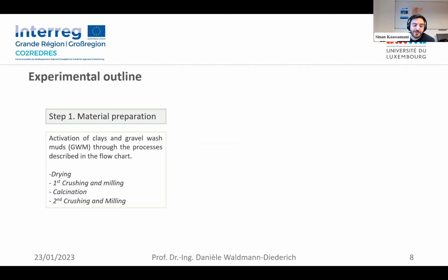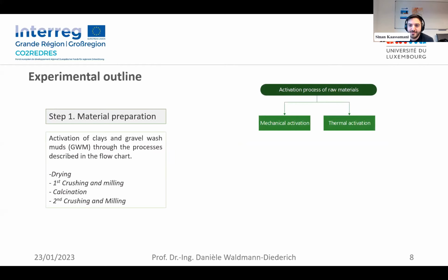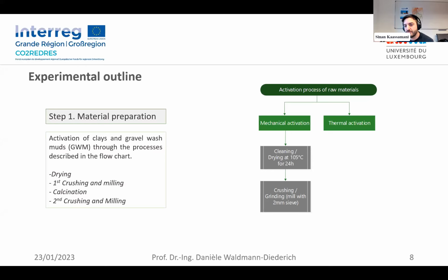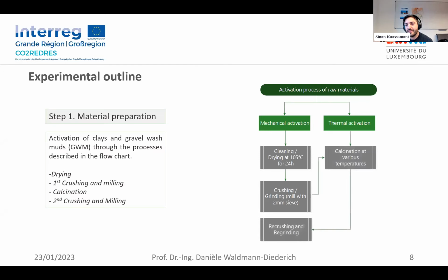So for our experimental outline, in the first step, we prepared these materials. In order to have better chances at activation of such clays and gravel wash muds, we follow the process of drying and crushing, and then calcination, and then crushing again. So it is of interest, of course, to have the finest possible material as a substitution. For the activation, as I mentioned, we had a mechanical activation and a thermal activation. By mechanical activation, we wanted to achieve a better fineness. So we had a drying at 105 degrees for all the materials for 24 hours, and then a crushing at a 2 millimeter sieve. And after this crushing, we had the calcination at 3 different temperatures, and then a recrushing and regrinding process. So this was the first flow chart.